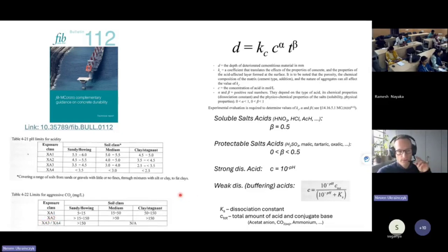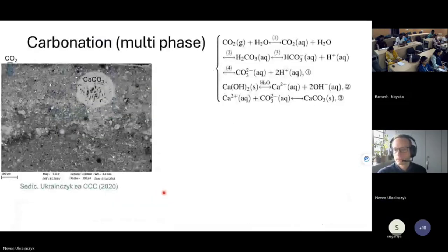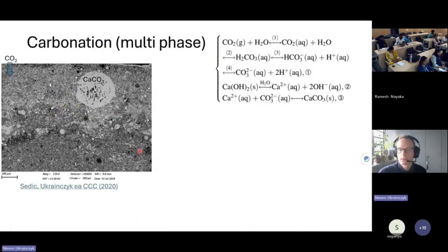Especially because all these exposure classes are made for Portland cements, and if you want to add slag or deviate from the standard, then you need to prove the acid resistance. And that's what we were doing here for them. So this was an example of the carbonation that I showed you also, I think on Tuesday, where this is the surface of the sample, and you can see calcium carbonate building on the surface and filling all these pores.